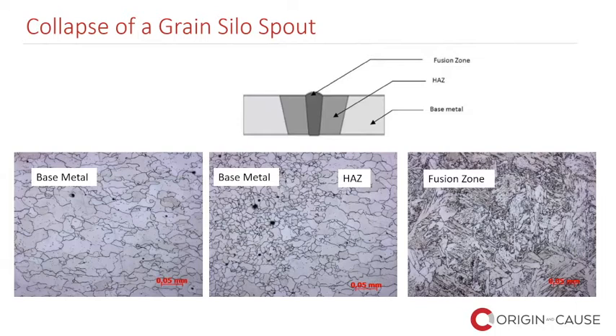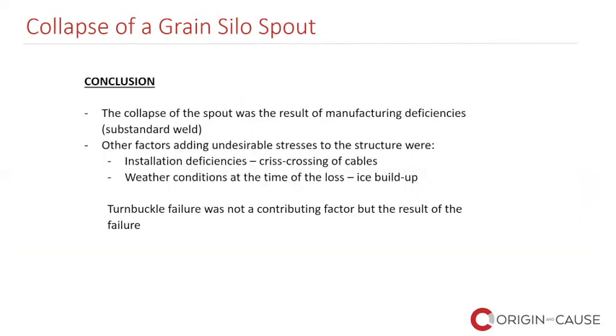Welds are very complex structures, and we analyzed its microstructure, and we found some porosity. Those black speckles are pores in the weld. Following gathering and analyzing the data, I reached the conclusion that the collapse of the spout was the result of manufacturing deficiencies, namely a substandard weld.